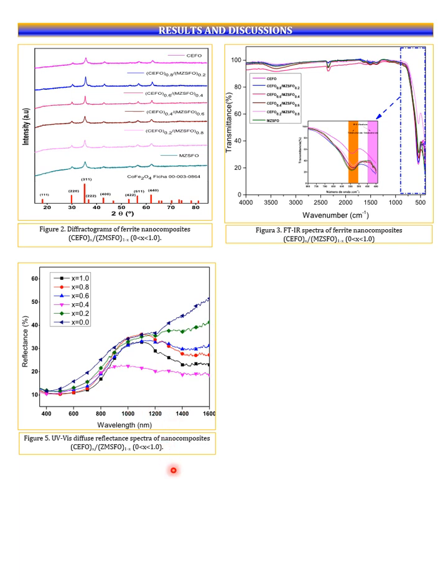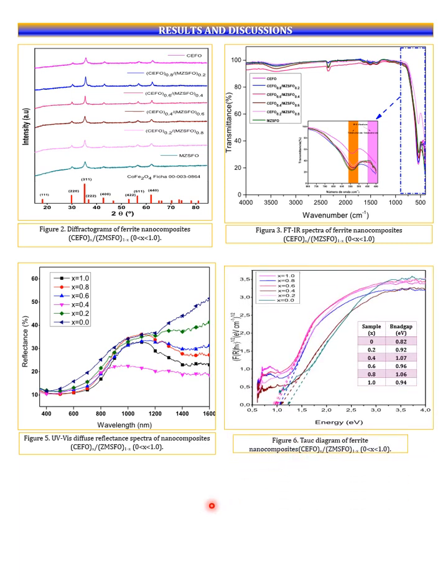Diffuse reflectance spectroscopy is the method used to determine the bandgap energy, Eg, of a powdered sample. From these data we can estimate the Eg of the material using the Kubelka-Munk function. Using a Tauc plot and plotting the Kubelka-Munk function versus photon energy, we are able to extrapolate the linear part of the graph to the x-axis and obtain the value of the sample where it intercepts the Eg value. All this analysis performed to estimate the Eg of the nanocomposites confirms that they have direct semiconductor properties.